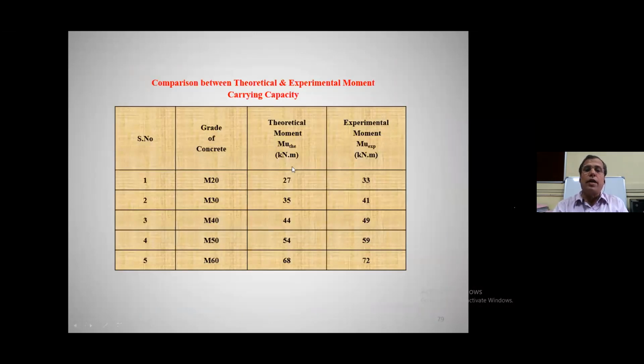And this is how we can understand the load carrying capacity. I can say the third column, you can see 27 is theoretical and experimental is 33. The moment of resistance experimentally done for the same geometry is 33, and theoretically is 27. Similarly for M30, 35, 41, 40, 44, 49, 50, 54, 59, 60, 68, 72. It means all the experimental values are more and the theoretical values are less. Okay, this is a good design. Theoretical values always should be conservative. Experimental values always should be more than the theoretical values.